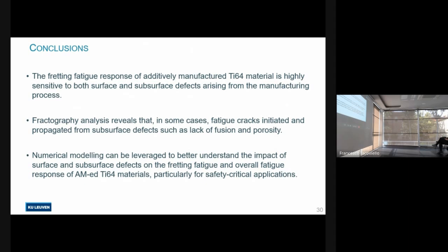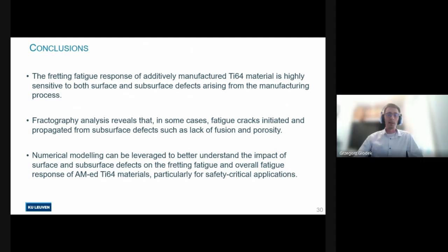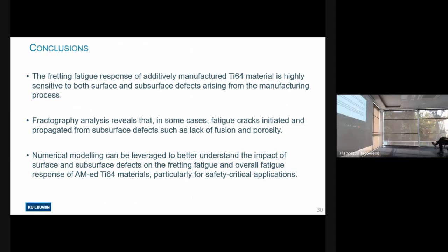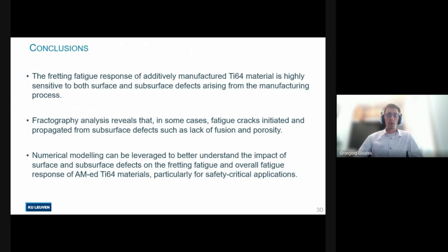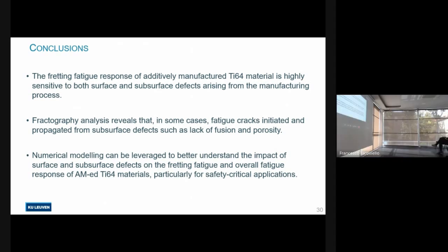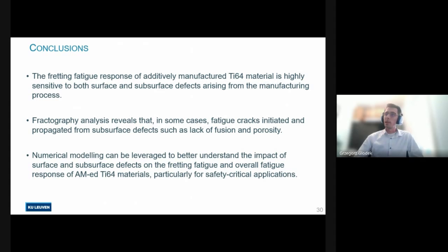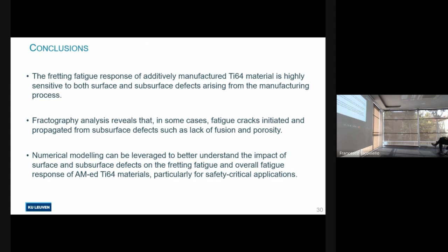The fretting fatigue response of AM Ti-64 is highly sensitive to surface and subsurface defects. It's entirely possible for the crack to initiate in the fretting fatigue region, but the failure can occur outside due to internal defects. The next step would be to incorporate such subsurface defects in the finite element simulations and see how they affect the lifetime and the stresses inside the sample.